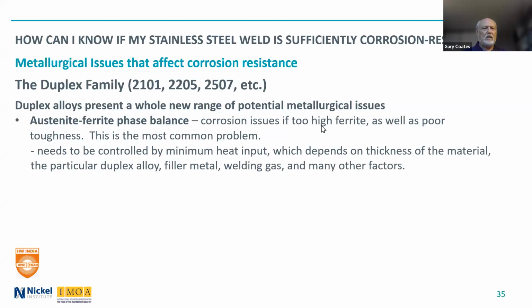Austenite-ferrite balance, corrosion issues. There are tremendous corrosion issues if you end up with too high ferrite, as well as poor toughness. It becomes brittle at low temperature. This is the most common problem. We can do a whole webinar on duplex welding. I think I've actually done one for IIW, but it needs to be controlled by many factors. Minimum heat input, which is completely different than austenitics. No minimum heat input for austenitics. There is for duplex alloys. The thickness of the material, the particular duplex alloy, the filler metal being used, the welding gas, many other factors.